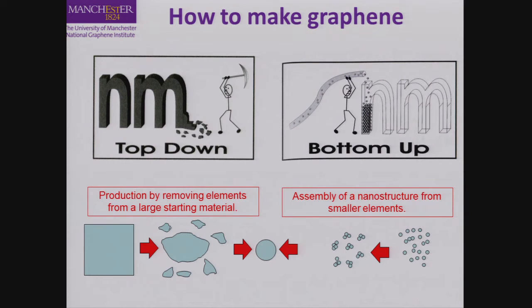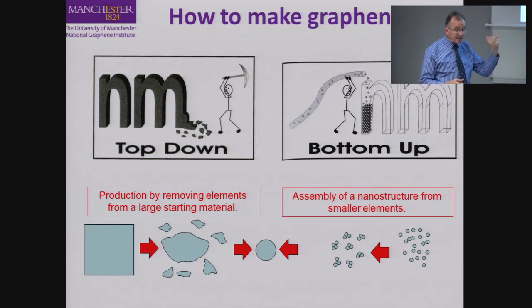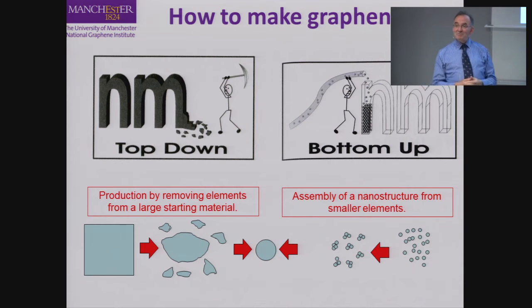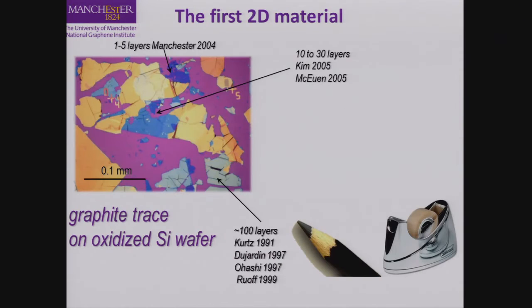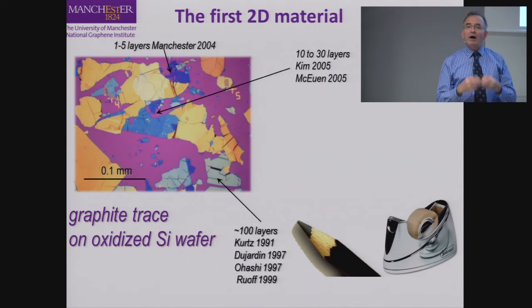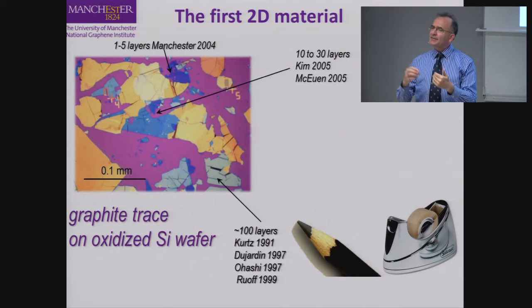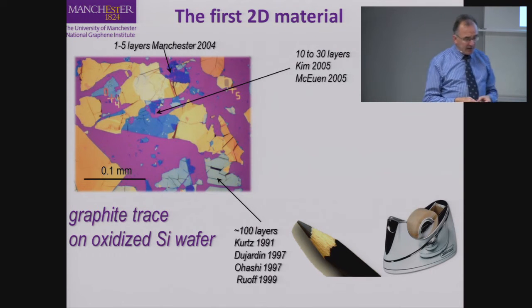Of course, the next challenge we have is how do we make graphene? One way to make graphene is to start with a top-down method, where we have a block of graphite and we try to break away layers of graphene. Or we can go from the bottom up, where we can build graphene atom by atom. And there are these two different techniques that can give you graphene. But if we look at the first two-dimensional graphene material, we have to go back to 1 to 5 layers of material identified by my colleagues at the University of Manchester back in 2004.